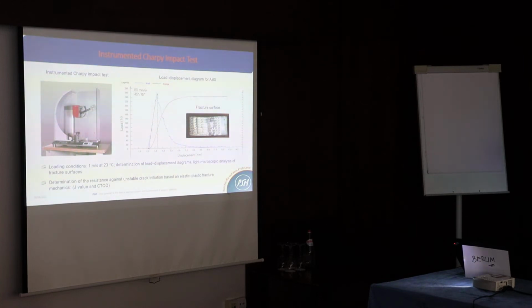This is very surprising because that's a little bit different from the case if you're using PLA. They are really brittle, but ABS is not brittle, so it's more advanced for applications. As you can see here, you have plastic deformation, a little bit of instability, and a high amount of stable crack propagation.